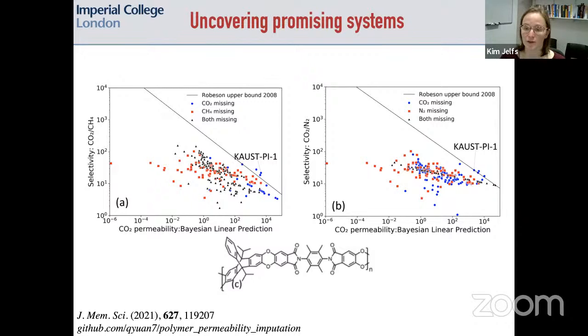And what you can see labeled is that we found this polymer that looked really promising, this PIM at the bottom. But when we went back, we saw that this had been reported previously in the literature, and it did indeed have the performance that we had predicted, a very good performance. But it had been done, and it hadn't made its way into the database.